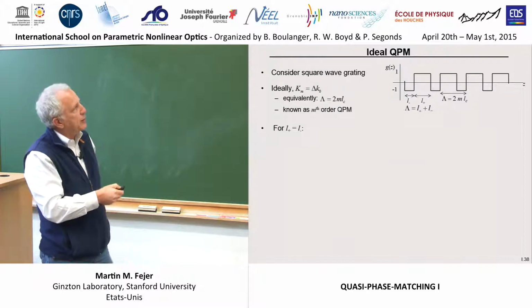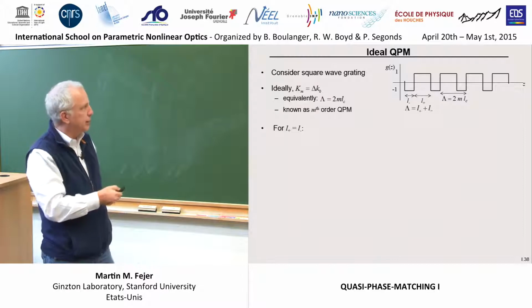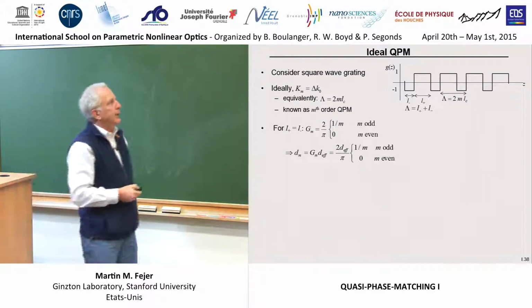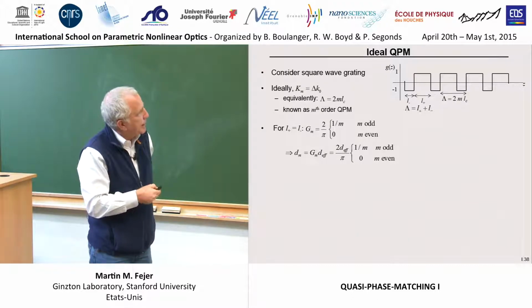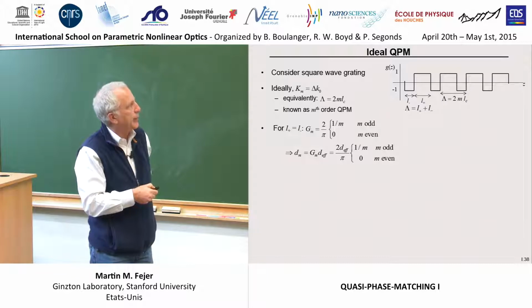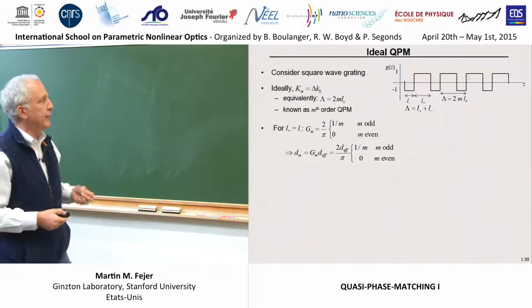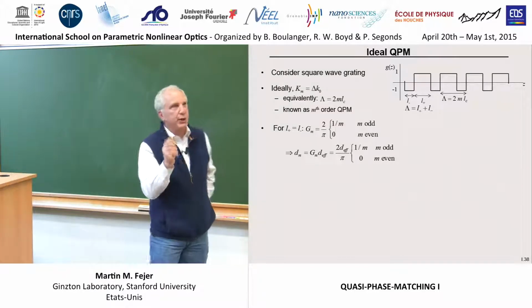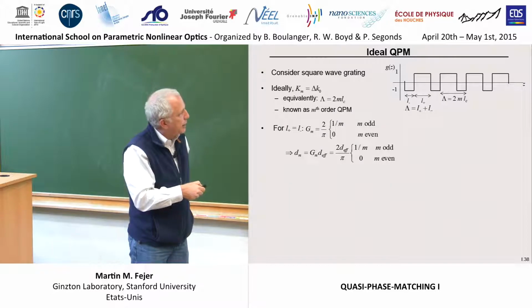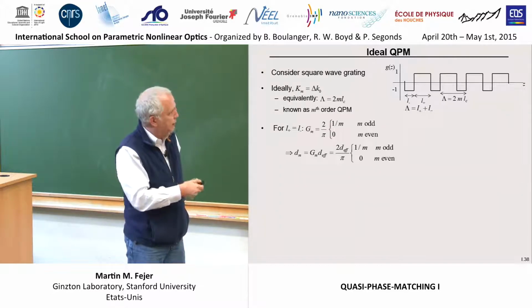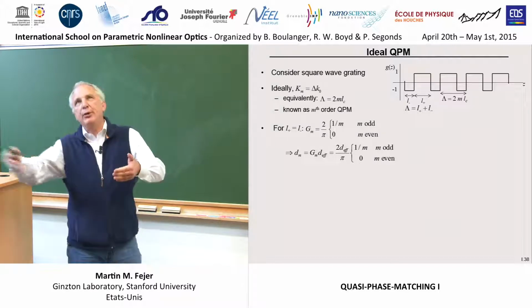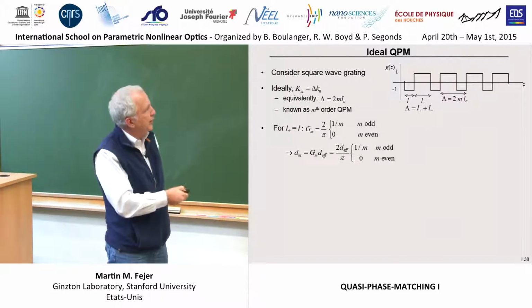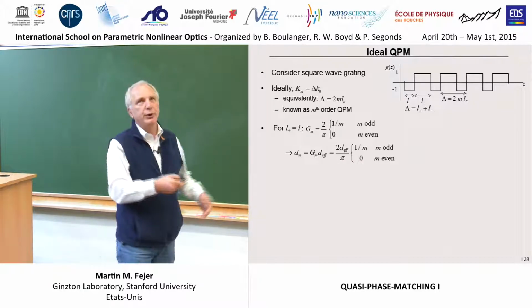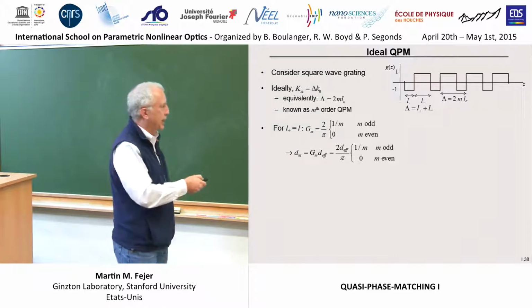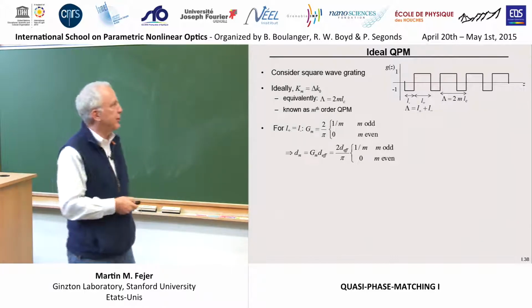So if we take the simplest case where the up and the down widths are equal, that's L plus equals L minus, you find that when you evaluate this Fourier series, this coefficient is 2 over pi times m for odd m's, and it vanishes for m even. Which says that the effective nonlinear coefficient that you're going to use in a quasi-phase matched case is smaller, in the best of all worlds if you're doing first order quasi-phase matching, by 2 over pi. And then if you use this higher order quasi-phase matching, you're going to further reduce the effective nonlinearity. The third overtone, you have 1/3, the fifth overtone, 1/5 as much effective nonlinear coefficient. We'll see a physical interpretation for that in a minute.